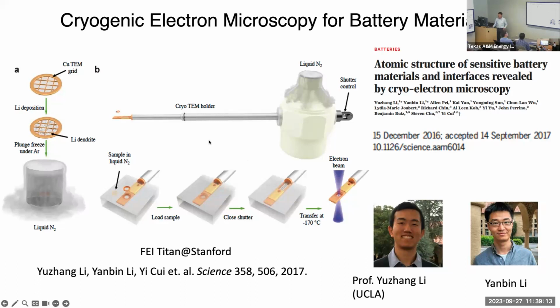We deposit this metallic lithium anode onto a TEM grid. We freeze it in liquid nitrogen without exposure to air. It's very, very cold, and we freeze all the motion right there. You stabilize the metallic lithium interface chemically, and without exposure to air, we developed this cryotransfer technique and put it into the TEM, the transmission electron microscope.